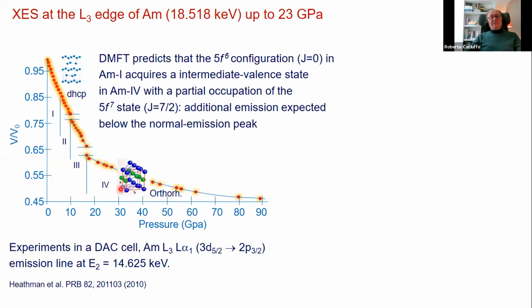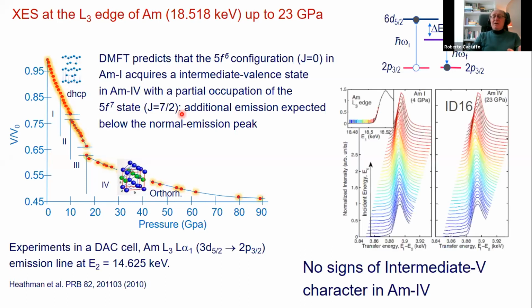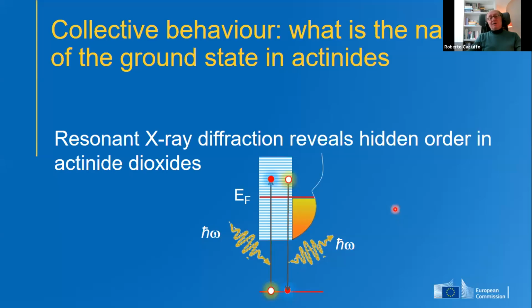Americium-4 is an orthorhombic phase, whereas in the double hexagonal close-packed americium-1 phase, the electronic configuration is non-magnetic 5f6. The mixture of the 5f7 state with a large moment was predicted, but in this case, you would expect an additional emission line below the main peak. And as you see in the left and the right panel, where the RIXS data are reported for the pressure corresponding to americium-1 and americium-4, this additional emission line is not seen. Then in this case, at least, dynamical mean field theory failed to describe the system.